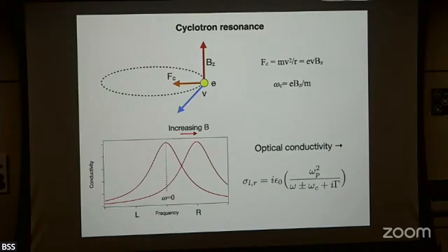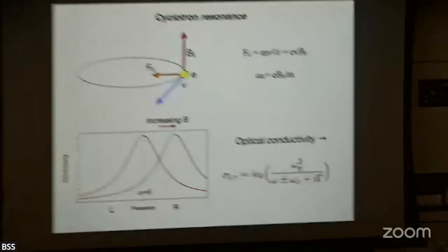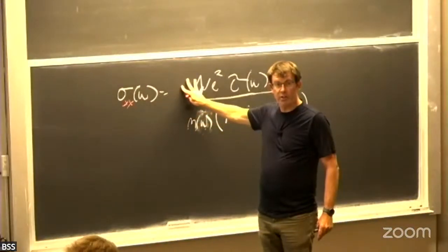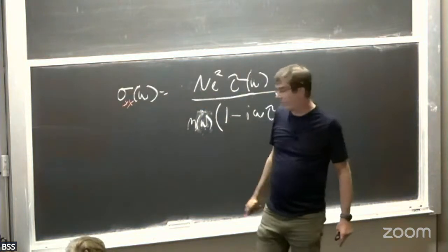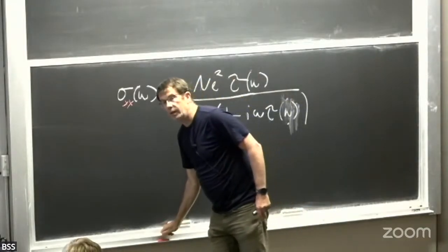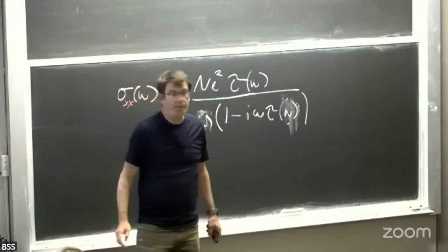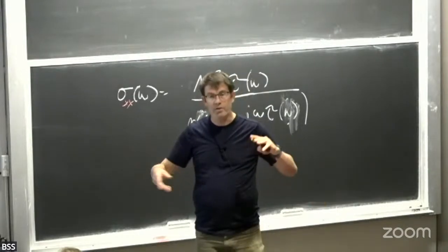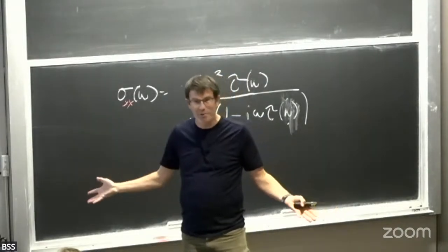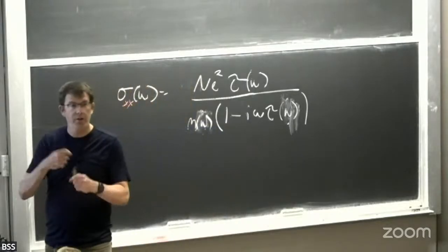We can think of the optical conductivity as I was writing something kind of very similar to this, but when I was writing this, I was thinking about the system, let's say without magnetic field, where I was thinking of it in XY coordinates, but I can think of it also as a response. This is a response of, say, current in the X direction to an electric field in the X direction. But I can also think of responses to right or left circularly polarized light. And that's, again, one of the advantages of the symmetry decomposition that I talked about, is that because we know the complex form of the symmetry properties, the complex form of the Jones matrix, we can measure in whatever basis we like and then transform into whatever basis we want.